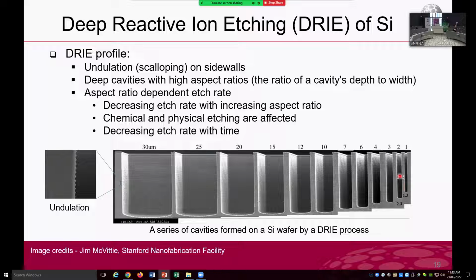Also, we can see these scallops, undulations formed on the sidewall, and that's kind of inevitable in the deep reactive ion etching process because we have to use etching and passivation steps. One scallop corresponds to one cycle of etching and passivation step.